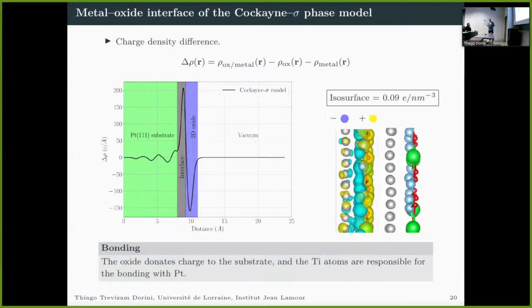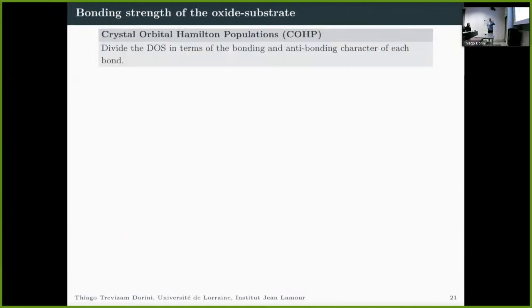And we can see on this 3D image the same characteristic, but it's interesting to notice that due to the oxide relaxation, the titanium atoms are moving closer to the platinum substrate. And we can see that it may have been the titanium atoms that are donating the charge, especially to the platinum first layer, which leads us to believe that first the bonds between the oxide and the substrate may come from these bonds, specifically the titanium and platinum, and the overall oxide stabilization may also come from this bond. So I would like to study more in detail the bond between titanium and platinum at the interface.